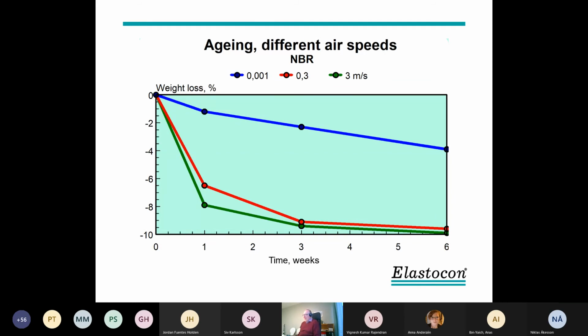We lose something. And what happens is that on the exhaust of the oven, we put in a condensation trap so we could get some condensation and make an analysis. And we found, not unexpectedly, softener and antioxidant. The nitrile has a quite volatile softener. We lost most of it in 3 weeks' time, about 10%. Even at low air speed we lost weight, but quite a bit less.